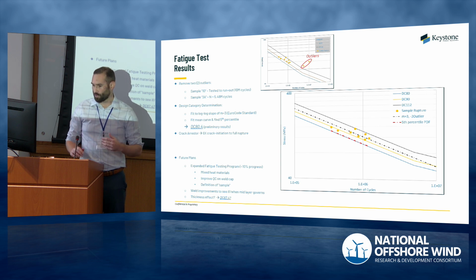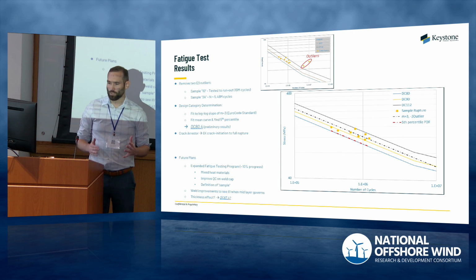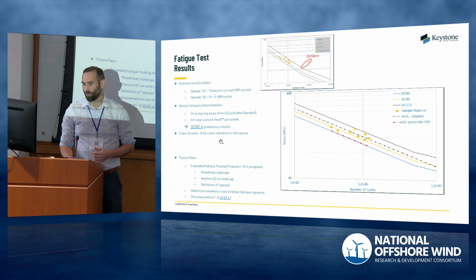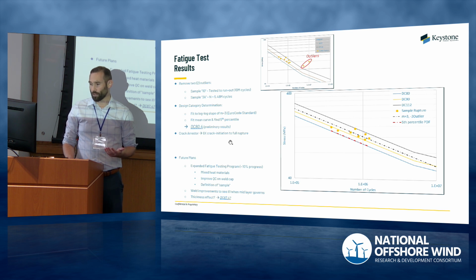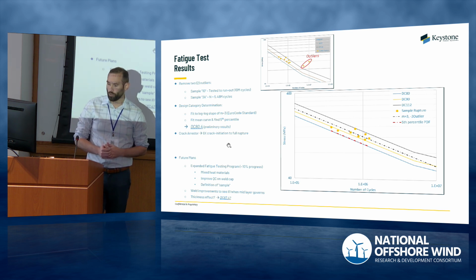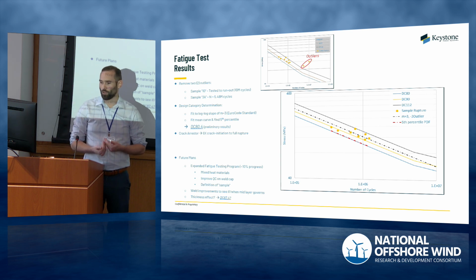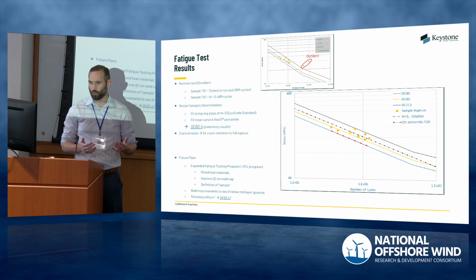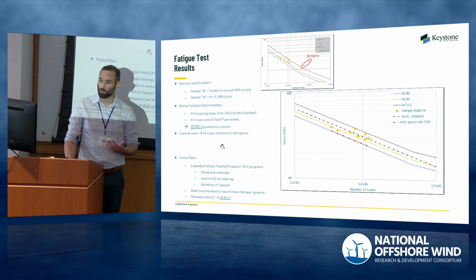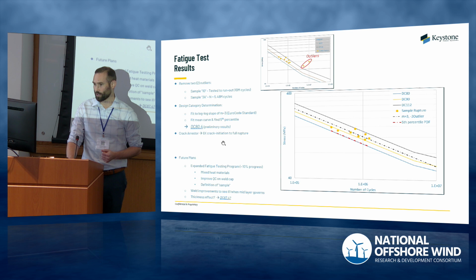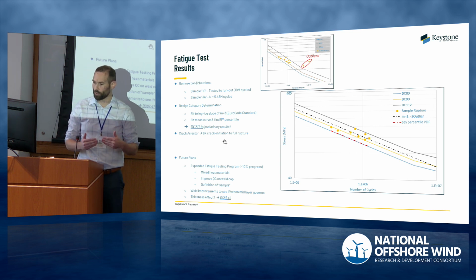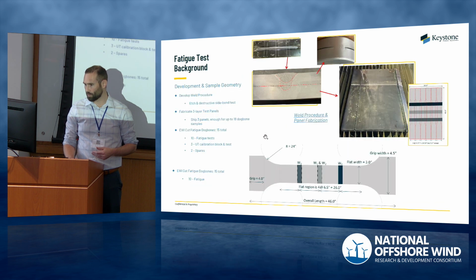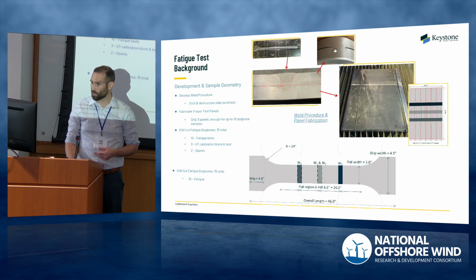After I did some analysis on our test results, I found that this actually passed as a design category 80, which was our target. There's a design detail of a weld into a backer, and that would predict a design category 71. So this is higher than expected, and some skeptics of this system suggested you would never even achieve that because of the sharp notch at this layer, where these layers are welded together.